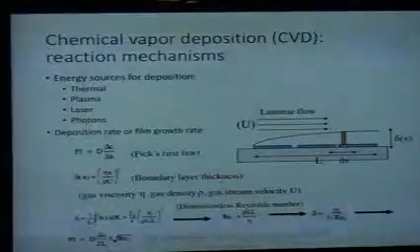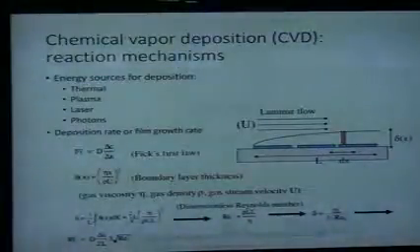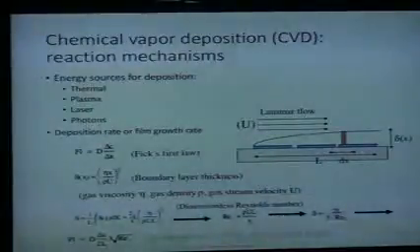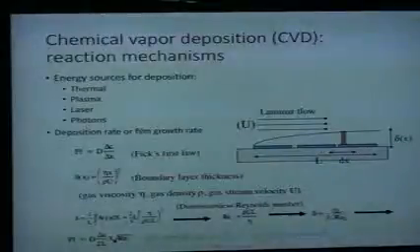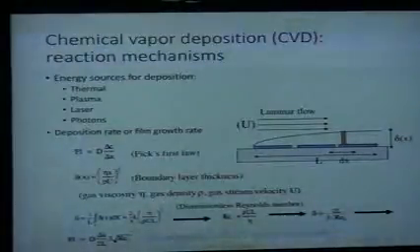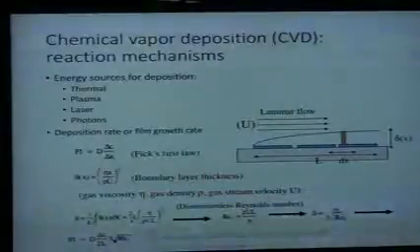One issue in chemical vapor deposition systems is non-uniform growth because of boundary layers. The boundary layer at the leading edge is thinner, so if my flow had a certain concentration of a species I wanted to deposit, I would get more deposition there than downstream where the boundary layer is thicker and diffusion has to travel farther to reach the surface. There's some interesting fluid mechanics that go with that, and it's a good application of fluid mechanics and mechanical engineering to what is, at its core, a high-temperature chemistry problem.